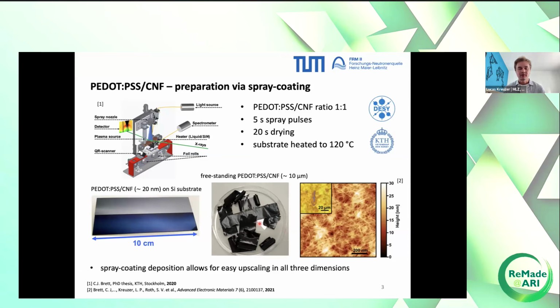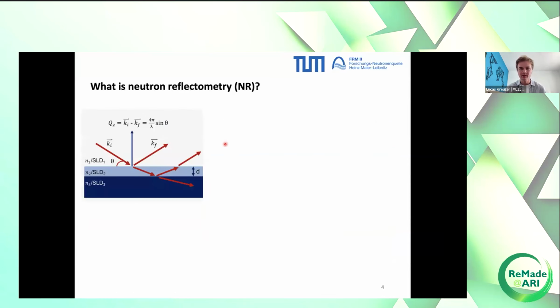And then we want to tackle already the first question. So do these films absorb water, and do these films swell? And this we can answer with a technique that is called neutron reflectometry. And just very briefly, the background of this technique, how does it work? You have a neutron, obviously. It impinges on your sample. It interacts with your sample, either gets reflected or it penetrates the film. The film is here indicated with this layer stack, just to mimic potential gradients within your film in vertical direction.